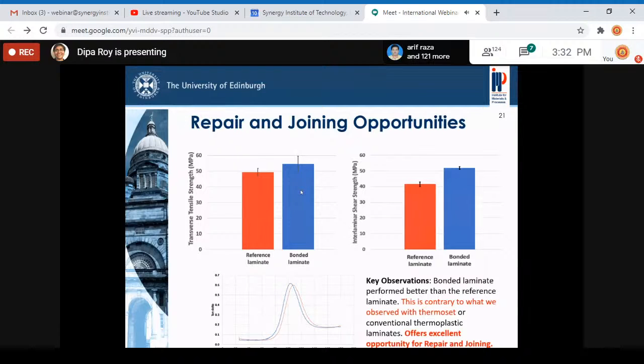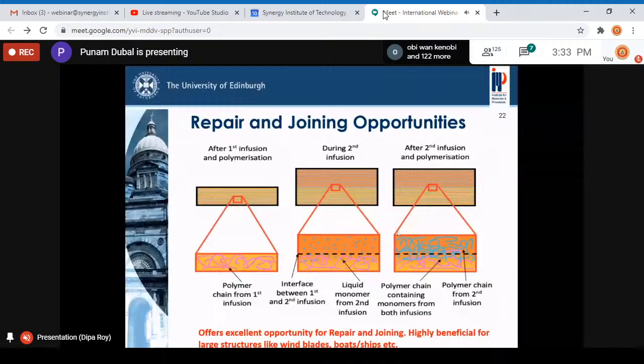But this is a very interesting observation, because whenever we are manufacturing in 2 steps, we are really getting some benefit. This is contrary to what we see in a conventional joined laminate. If we join a conventional thermosetting laminate or a thermoplastic laminate, we always have a weak point in the joining plane. Normally the stress concentration is much higher there and the failure occurs from that weak bonding line. But here we saw just the reverse, because the overall property was really enhanced. We were very delighted when we saw these results.